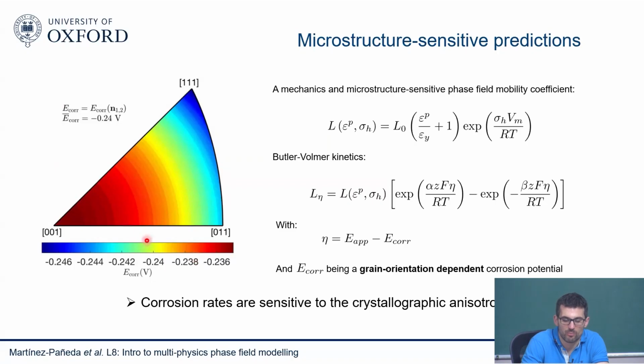To do that, we develop, I would say, a mechanics and microstructure sensitive phase field mobility coefficient. So you have here the mechanical term. Now you consider Butler-Volmer kinetics, and you define the overpotential as a function of a grain orientation dependent corrosion potential. So Butler-Volmer kinetics are very typical in these kind of electrochemical problems. And then the idea is that you have an overpotential, and in that overpotential, you bring in a grain orientation dependent corrosion potential. And this is the dependency, which is based on experiments, basically. They did some experiments for different orientations, and they measure the degree of corrosion, and you can fit those experiments. You can determine what is the orientation of your grain, and then you can bring this into the picture.